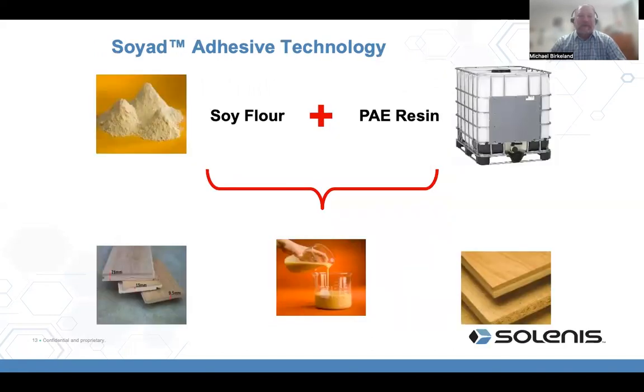Next slide. So the soy adhesive technology really is based on that idea. Soy flour plus PAE resin will give you an adhesive that is really pretty good at bonding wood and lignocellulosic materials. We typically target only interior applications. The reason for that mostly is because certainly in North America, wet wood failure is a real piece of the equation in terms of getting to pass that. And soy flour remains fairly hygroscopic. It absorbs water, it softens, and it's tough to get that material to be as strong as the wet wood. So most of our work is focused on interior applications. Next slide.